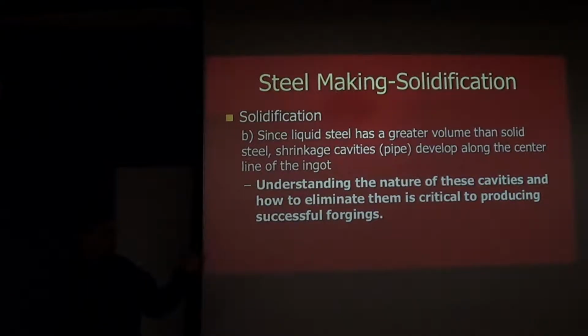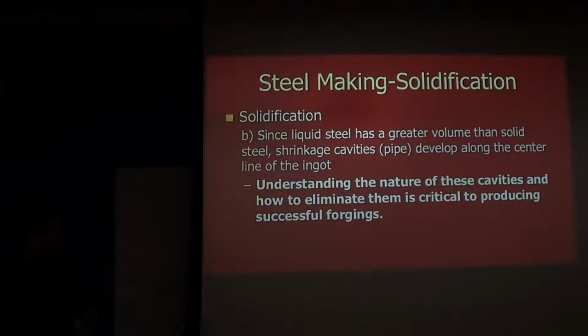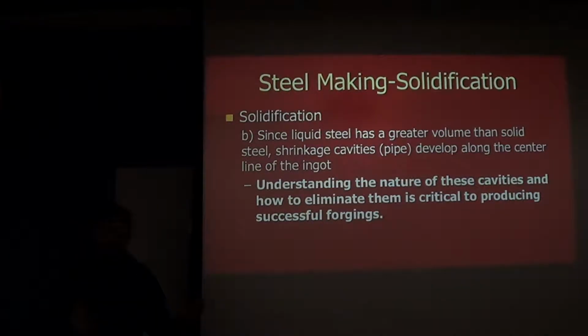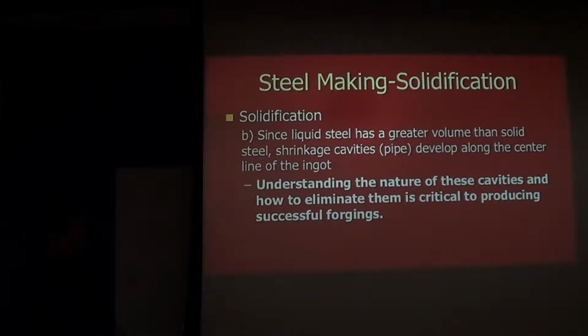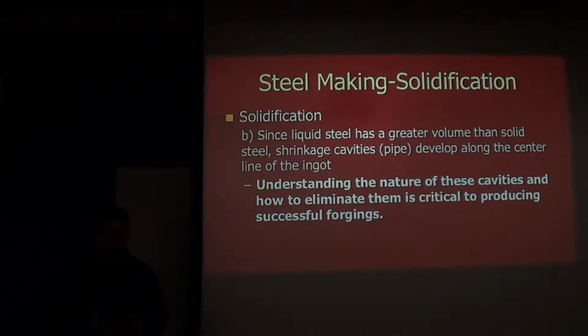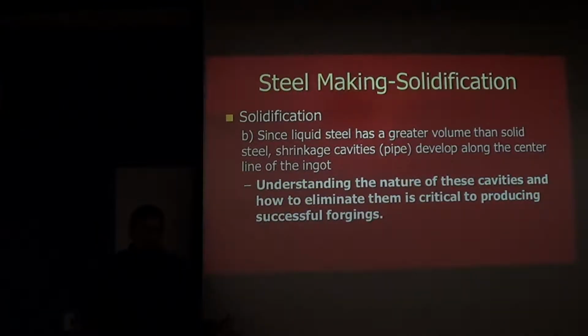We just talked about changes in composition, but I touched very briefly on the fact that when you go from liquid to solid, there's a change in volume. Steel shrinks, so you end up with these shrinkage cavities. So the ingots that we receive all have holes in them, and they're oriented along the center line. The terminology that's used in the forging world, we call that pipe. In the foundry world, that would be called a shrinkage cavity. It's the same thing. You have the last region to solidify. There's nothing there to fill the void, so you end up with a void.